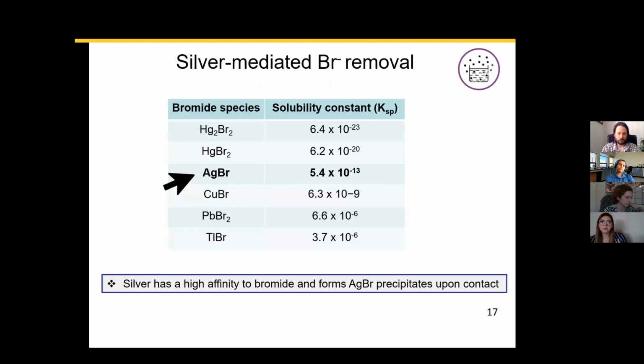So we looked at the different bromide species that could be precipitated, but we saw that we didn't really want to use mercury or copper or lead, because we know that these elements are very toxic. And so we wanted to look at something that has a high affinity to bromide, but is not as toxic. So we actually decided to use silver. We know that silver has a very high affinity to bromide, and it tends to form silver bromide precipitates upon contact.